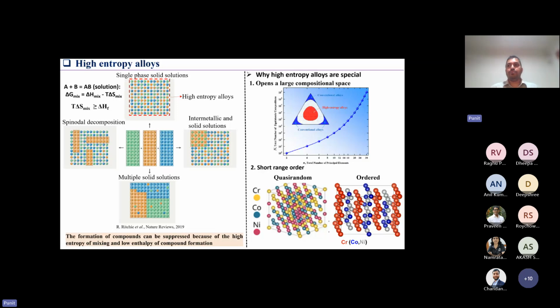For example, chromium, cobalt, nickel: if you look at these elements, chromium is BCC, cobalt is HCP, and nickel is FCC. And when you mix all these three you end up with an FCC crystal structure. So people did this first principle calculation, and they realized that actually this material should never be stable as an FCC alloy at room temperature, because you have negative stacking fault energy if you calculate it with first principle calculations. And the way they can actually realize the formation of this FCC crystal is by inducing this ordering inside the material, which increases the stacking fault energy to